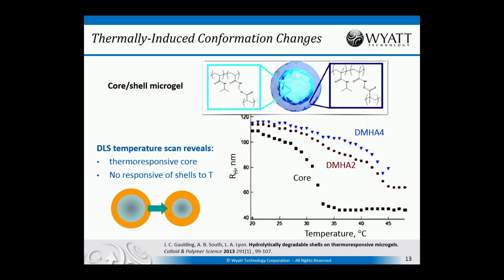So what we have here is measurements of the average value of the radius, RH, as a function of temperature, ranging from 20 degrees up to 45 over here. And if we look just at the black squares, which are just the core alone without the shell, we can see that the core is highly thermoresponsive. Its radius changes from about 110 at 20 degrees, going through a transition with a central point about 32, and then goes down to about 45 or 47 nanometers. So the core part of this core shell microgel is quite thermoresponsive.